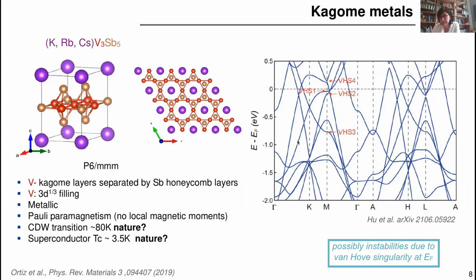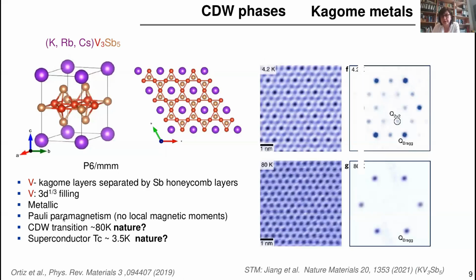Now, what do we know from experiments about this charge density wave transition? Here I'm showing the STM results from the group of Jiang, at 80K. This is the picture of this charge density wave transition, and we see here the Bragg Q peaks, which form a perfect picture that you expect for this kagome lattice.